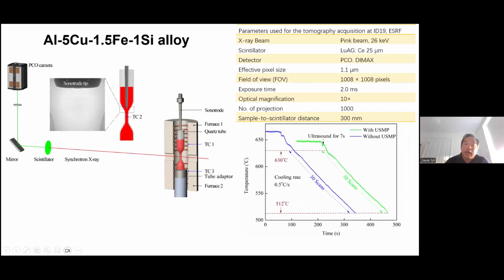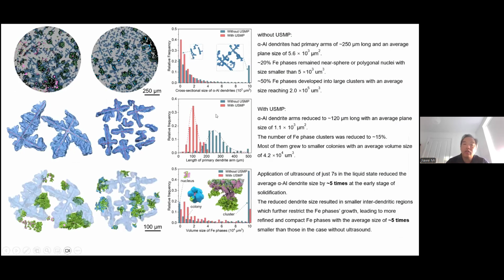And we also looked at this particular alloy. I showed you how we understand the liquid structure evolution before nucleation and after nucleation, how these different types of iron-containing intermetallics evolve. But when we apply the ultrasound to this particular alloy, and we did this again at ID19, what is happening is shown very clearly. Without the ultrasound, and with ultrasound, this is the sum of one projection after the machine learning segmentation. You can see the effect on the dendritic structure.